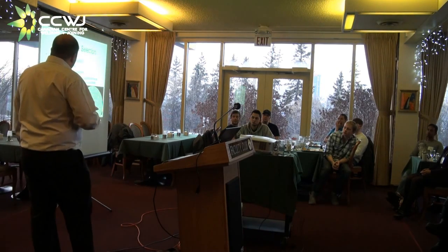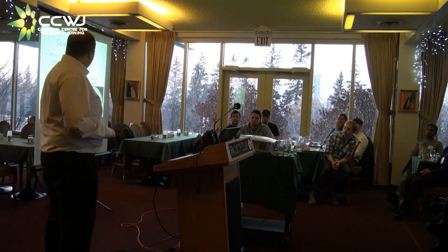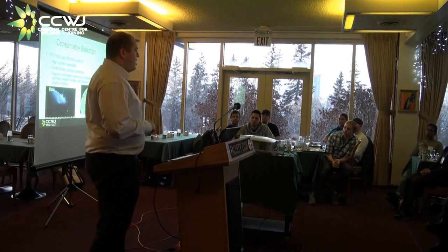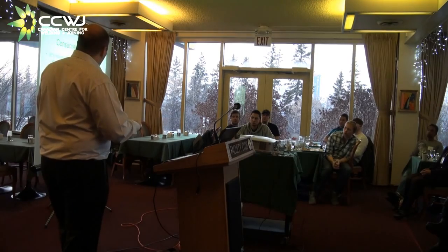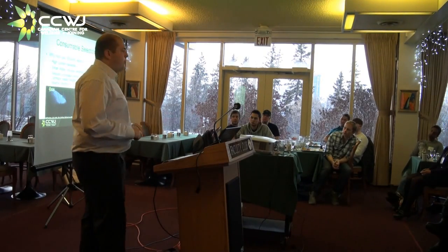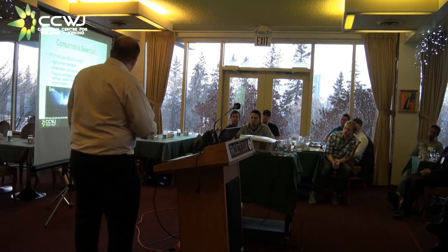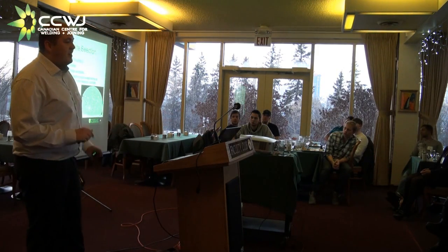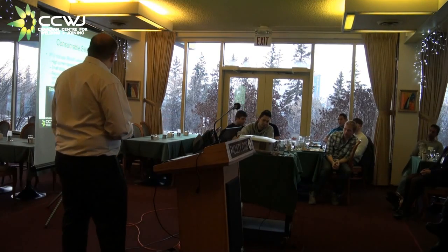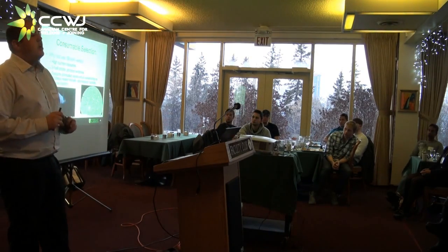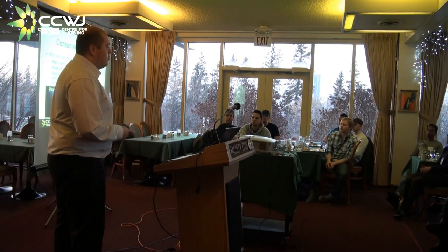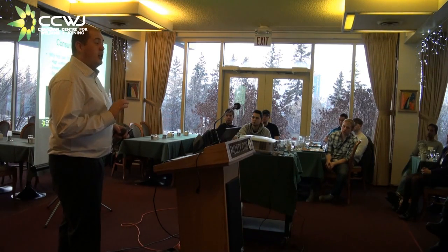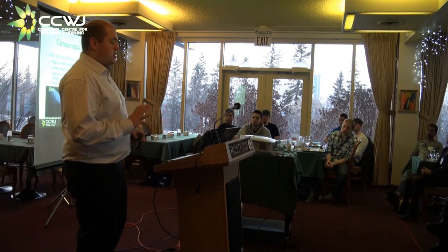So this is the video we shot in our lab of, I think, wire C or D, one of the very thin sheath ones, in short circuit mode. And while we did get okay weld deposits, the weld bead is not ideal. As you can see, there's a lot of undercut at the weld toes. It's not good. And also, the process stability was very hard to achieve, especially considering our end game was to have the maximum tungsten carbide in the weld deposit. For this particular consumable, the stable metal transfer range for a good deposit was about 20 inch per minute wire feed speed, which is extremely small and not ideal.